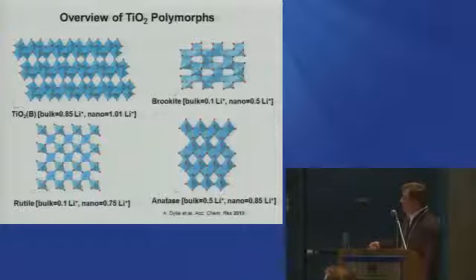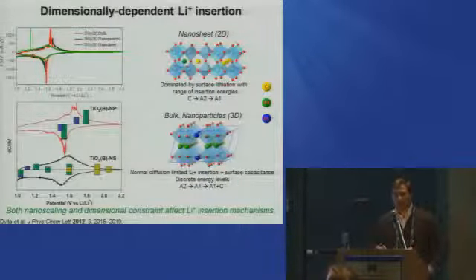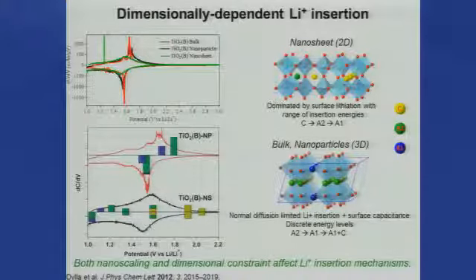Okay, but of course, then you can ask the question: where does the lithium sit in these crystal structures, and what is the oxidation state that governs the lithium-ion electron transfer kinetics of these sorts of processes? So in one system, we were actually able to come up with a very precise synthesis where we could make titanium nanosheets that were two-dimensional analogs of something like graphene, okay? And this was done by actually using ethylene glycol and isopropoxide, and the ethylene glycol binds to one particular crystalline face, and it limits the growth into two-dimensional sheets. We could also then use the same precursors in the absence of ethylene glycol and make nanoparticles of the same phase. So we had control over both the morphology, the dimensional confinement in this case, but also the particle size.